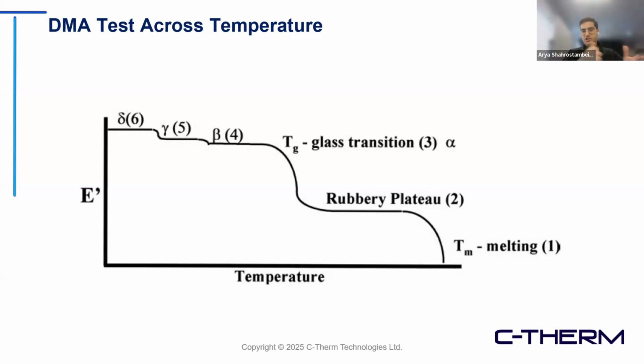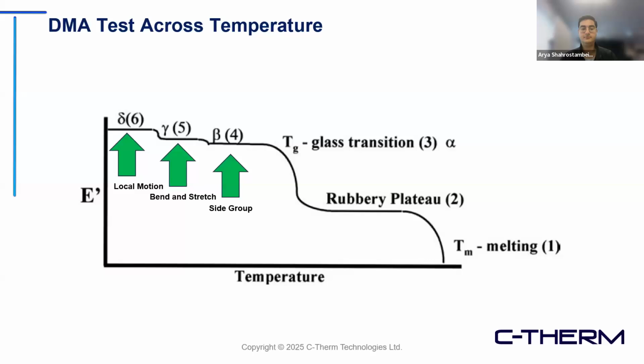But as you can see, there are different stages to that. So before glass transition temperature, we all know material is stiffer, but we don't know what's happening exactly at each different stages. DMA is the only technique available that gives you details about transitions, secondary transitions lower than glass transition temperature. For example, before glass transition temperatures, you can see 3 different stages of the material secondary transition. So the beta transition gives you information about the side group movement of a polymer chain. And the gamma gives you a bend and stretch of the polymer chains. And the delta gives you information about local motion.